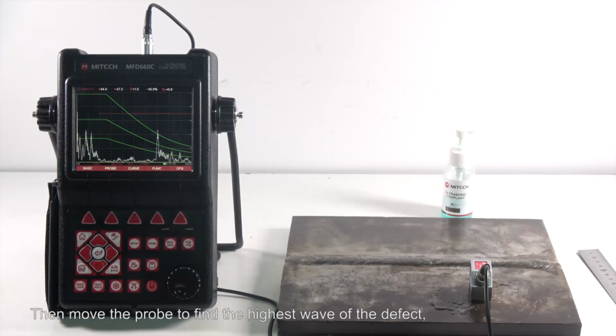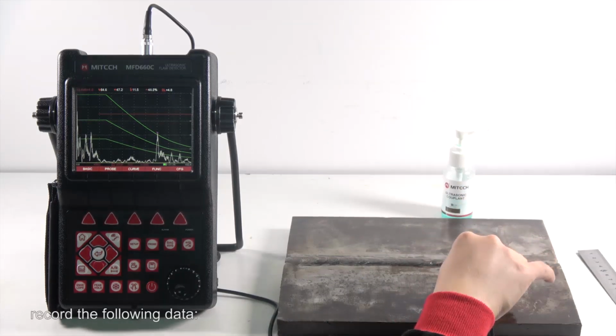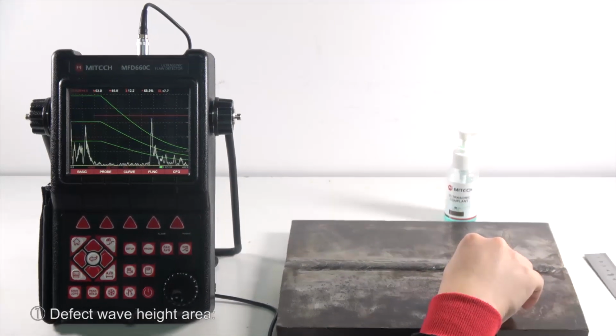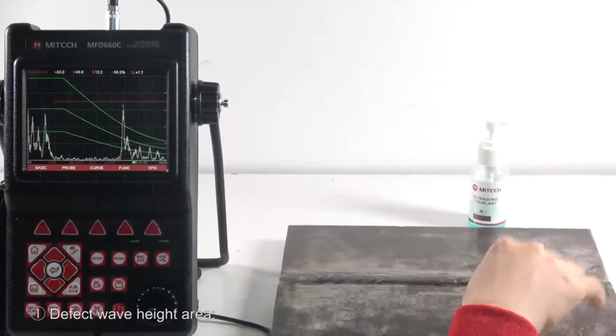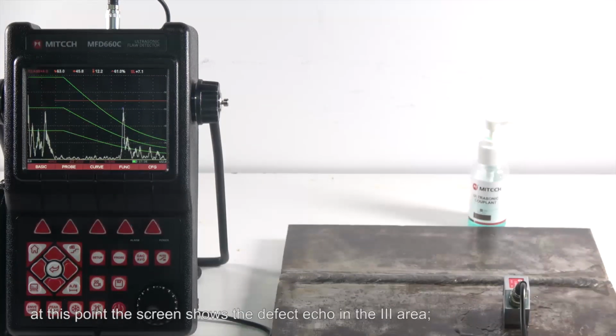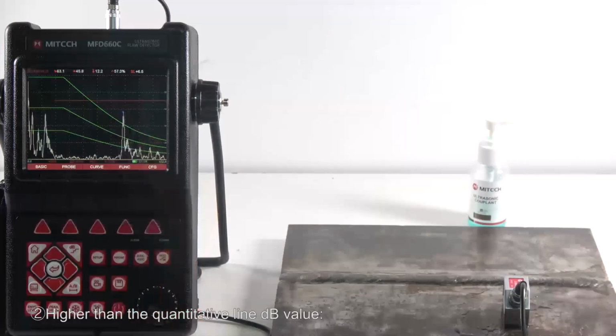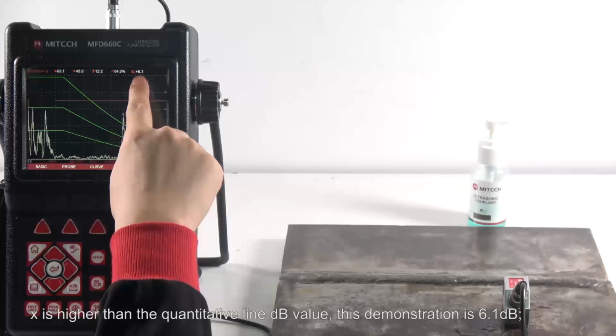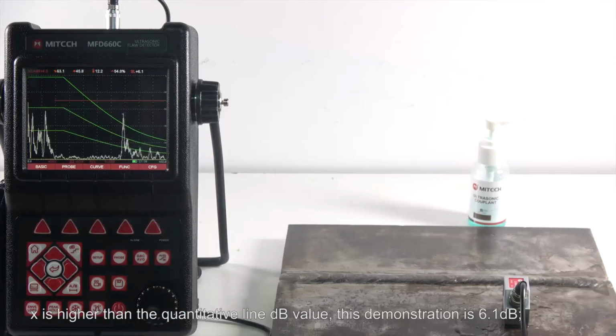Then move the probe to find the highest wave of the defect, and record the following data. Defect wave height area: at this point, the screen shows the defect echo in area three, higher than the quantitative line. The upper right corner of the screen shows SL plus X, where X is how many dB higher than the quantitative line. This demonstration is 6.1 dB.